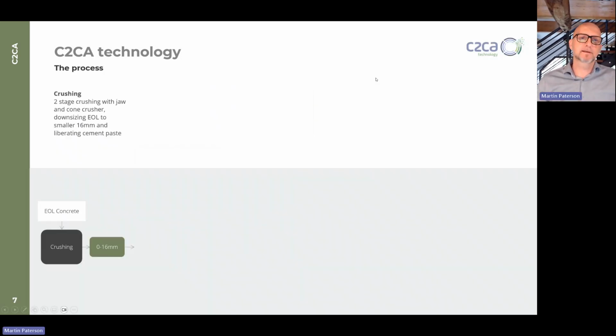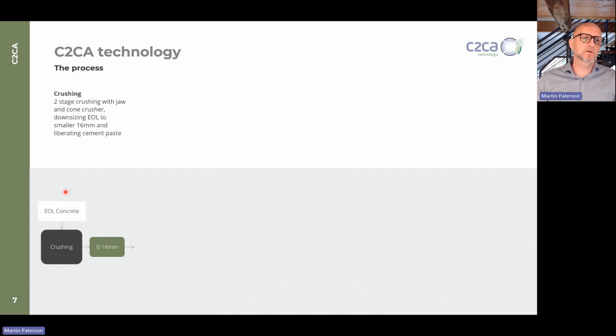The process, and let me get out a pointer here. So what we do is we receive end-of-life concrete here. We're not doing the demolition or anything; this is done by partners. So we receive the end-of-life concrete at site. We do a 2-stage crushing. First stage to simply downsize the bigger concrete elements, the second stage more to rub off the cementitious paste from the stones. So it's no impact crushing, it's more attrition that we're doing here, and we have developed a special process for that. And we get 0 to 16 millimeter out of this 2-stage crushing.